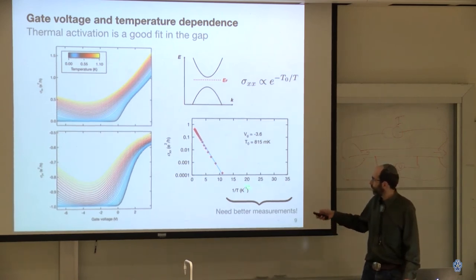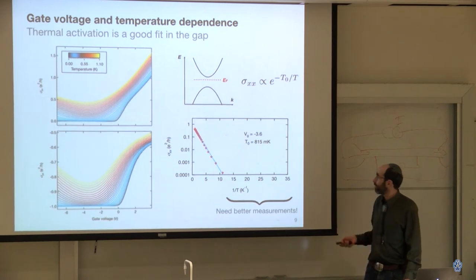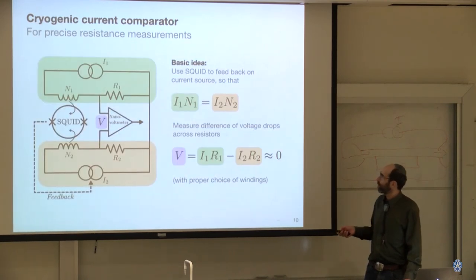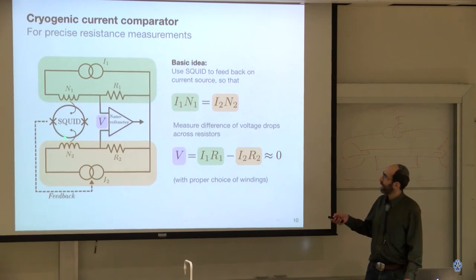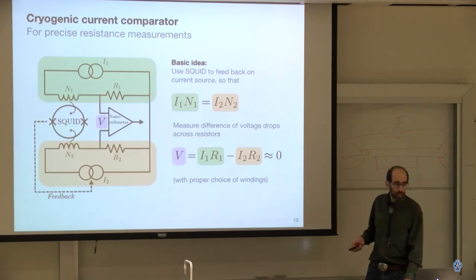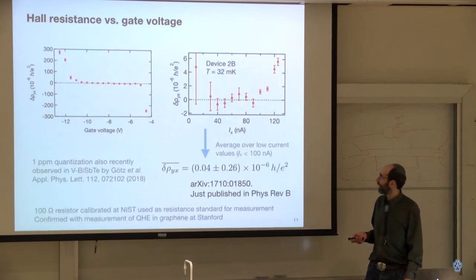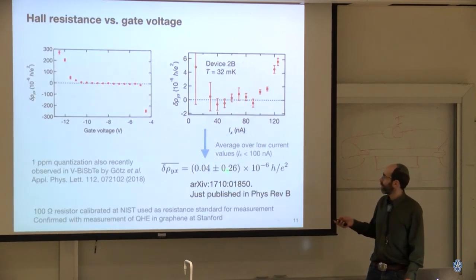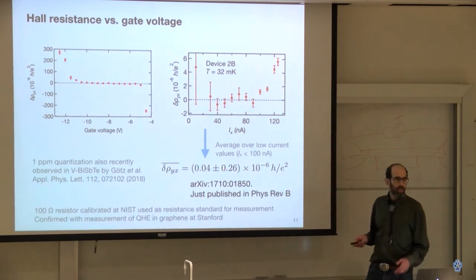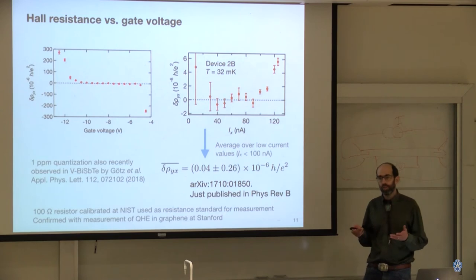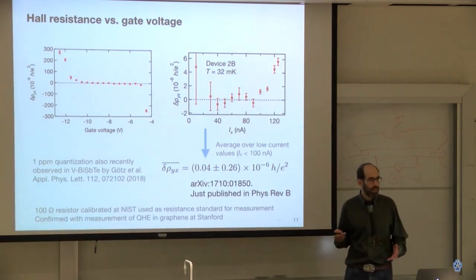So we'd like to be able to look at very low temperatures. We need better measurements, and so we used a tool that's called a SQUID-based current comparator. Something that the professionals at the National Institute of Standards and Technology shared with us and helped us use. With that, we were able to make a measurement to about 2 parts in 10 million. So we're getting close to the levels that are metrologically important.